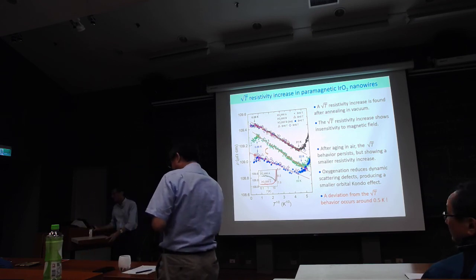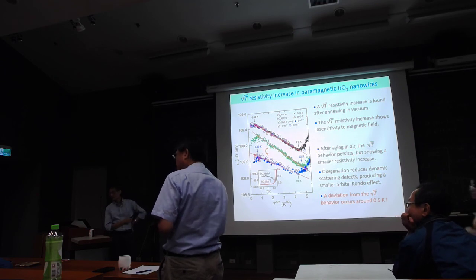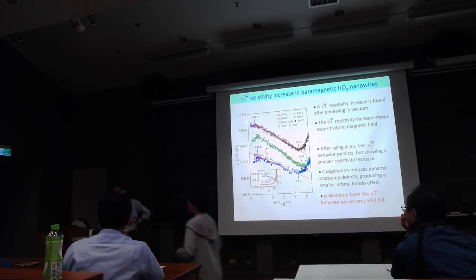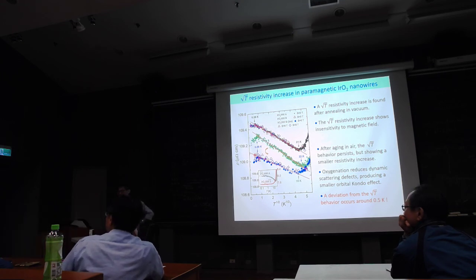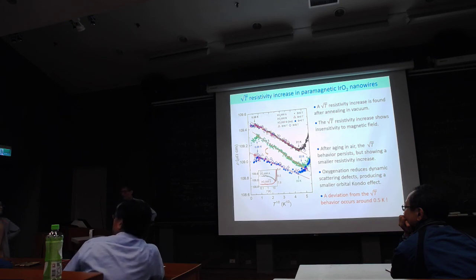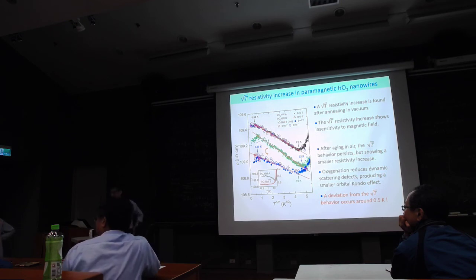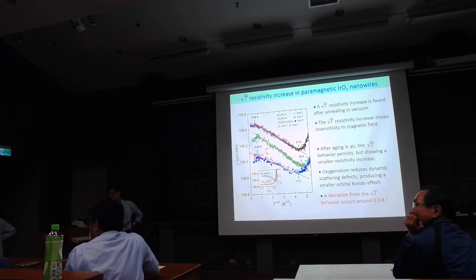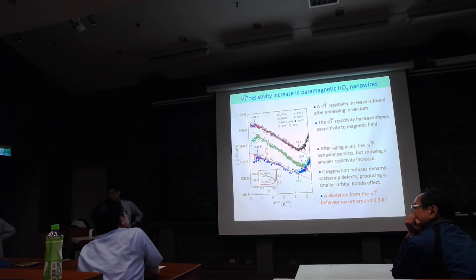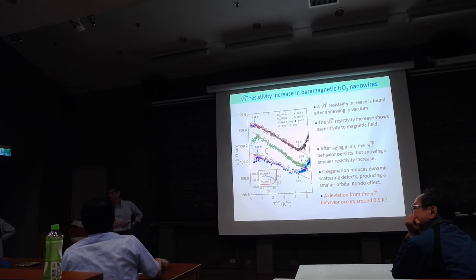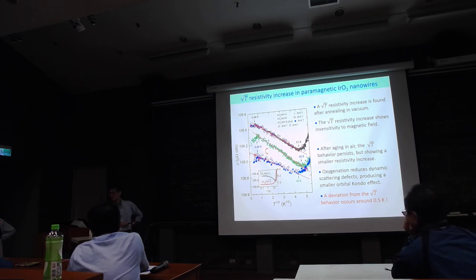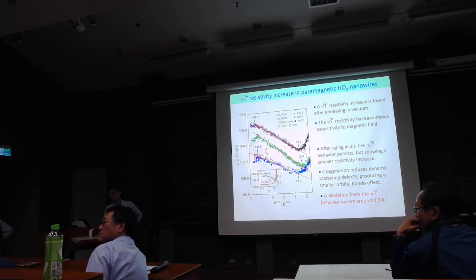I'm curious about the statement that the orbital Kondo effect does not depend on magnetic field. Right. In the example, say the oxygen vacancy, you have an unpaired electron, right? So if the defect has an unpaired electron and you apply a magnetic field, the unpaired electron will align its polarization along the magnetic field. Therefore, you have the magnetic property. And so electron scattering with the polarized impurity, the scattering coefficient or scattering cross-section, will be different. So intuitively, I would expect the resistivity would depend on a magnetic field, even though this picture shows it does not.